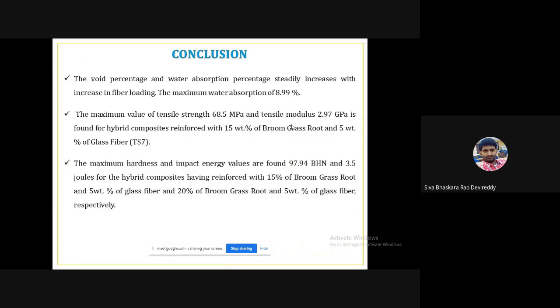These are the conclusions. The void percentage increases. The maximum water absorption is found to be 8.99%, the maximum tensile strength is 68.5 megapascal, the maximum tensile modulus is 2.97 gigapascal, and the hardness and impact energy values are found to be 97.94 Brinell hardness number and 3.5 joules.